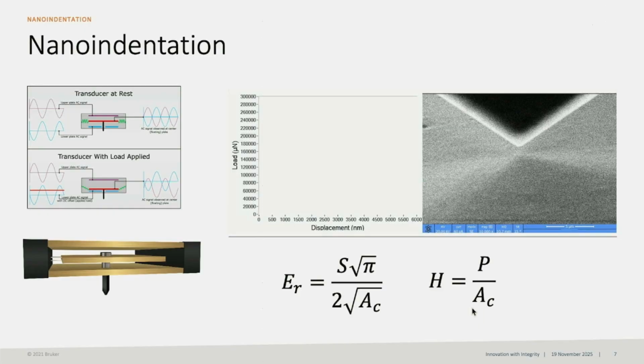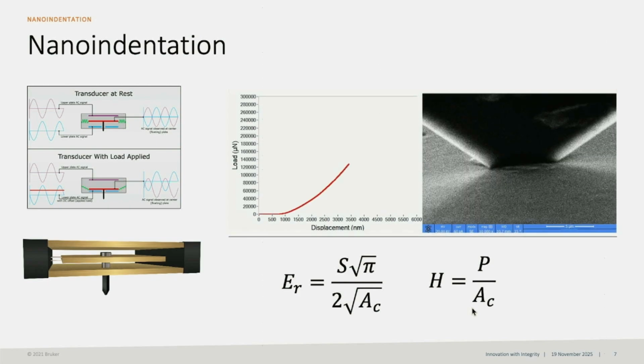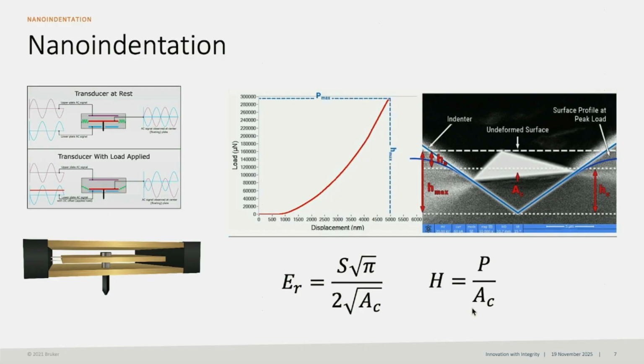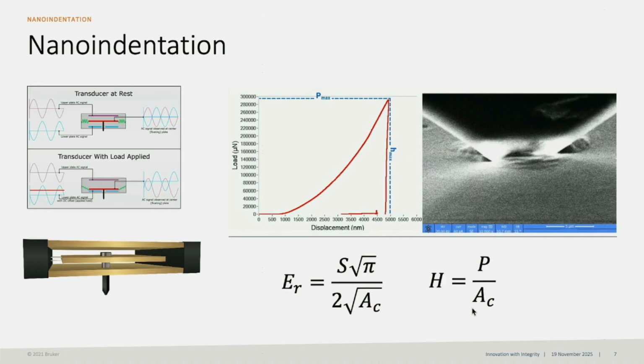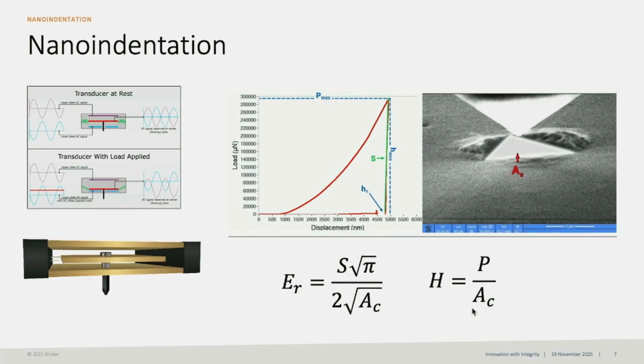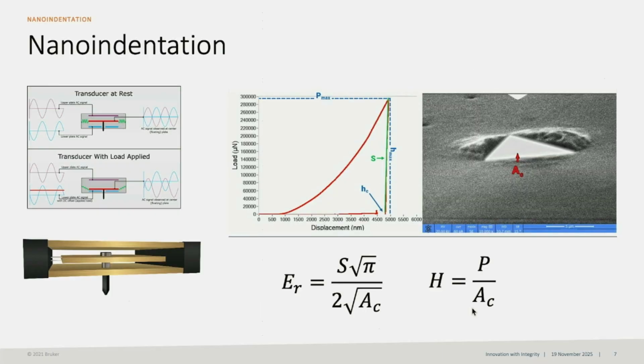And this is a video showing nanoindentation inside of the SEM. So this is the probe, just as I said, we indent into the material and calculate the contact area, then we get the elastic modulus and hardness. So this gives you the image of how accurate our nano indenter is. You see, this is the 5 micron scale bar. So the indentation mark is maybe around 5 micron, a little bit big. This is a larger indentation for nanoindentation. Normally, our indentation mark is below or just equal to 1 micron. This is very difficult to see with an optical microscope. That is the reason we have to use the SEM.